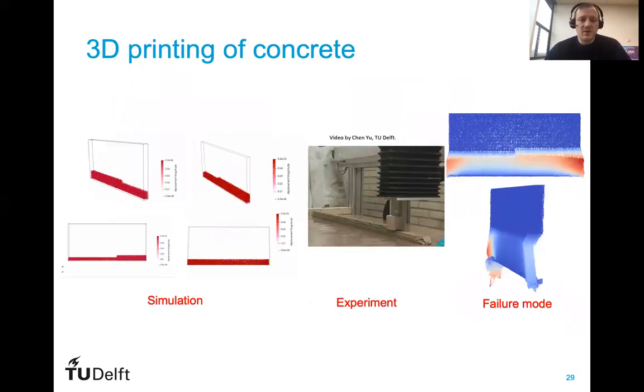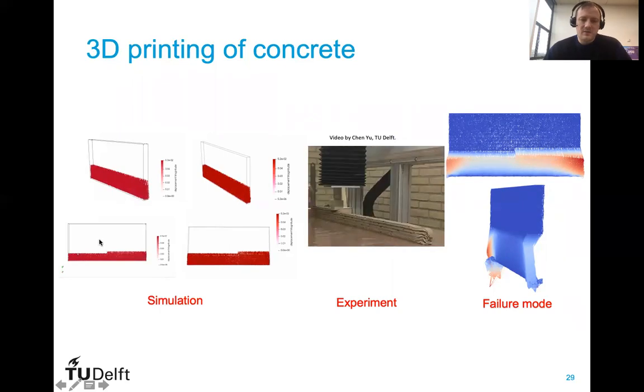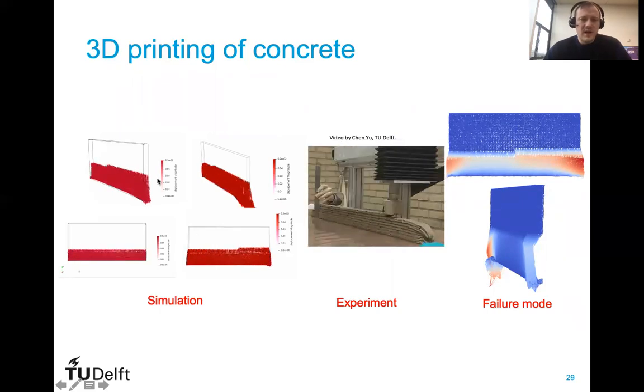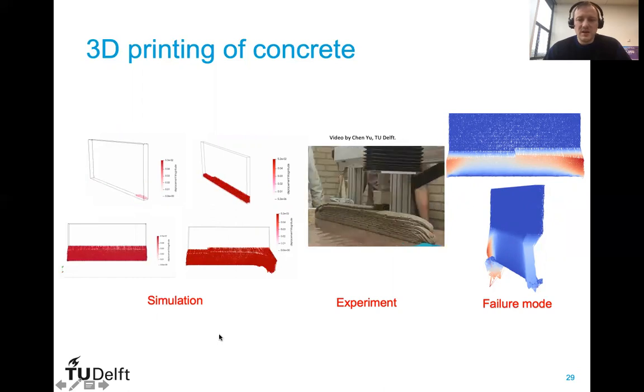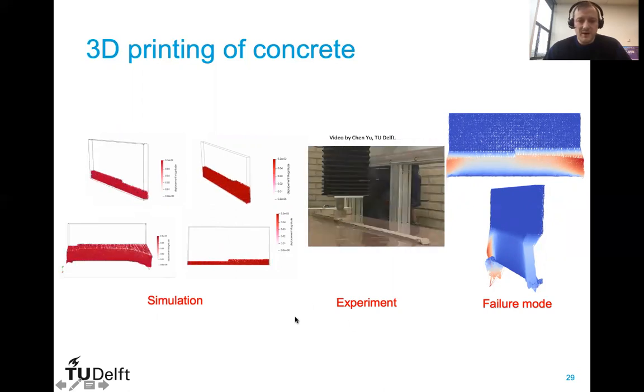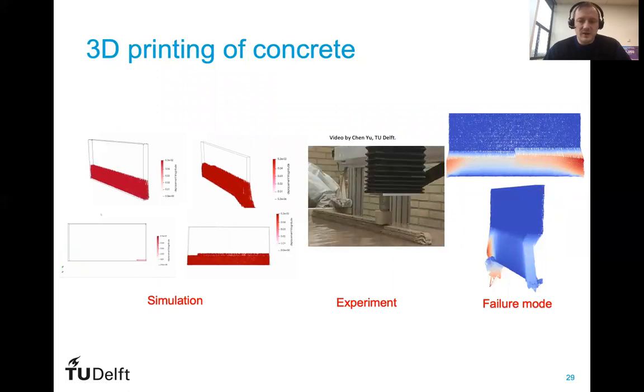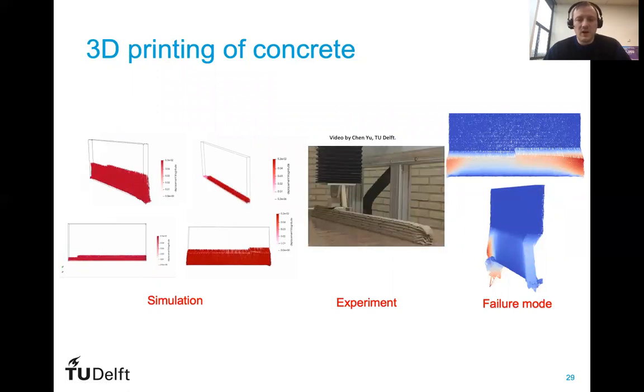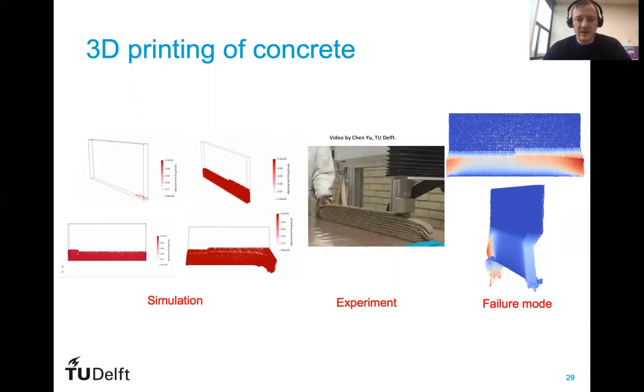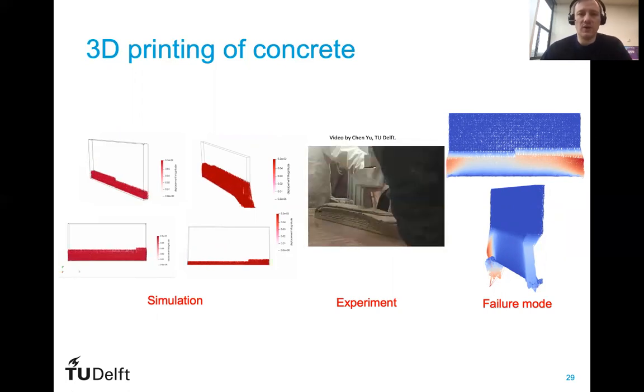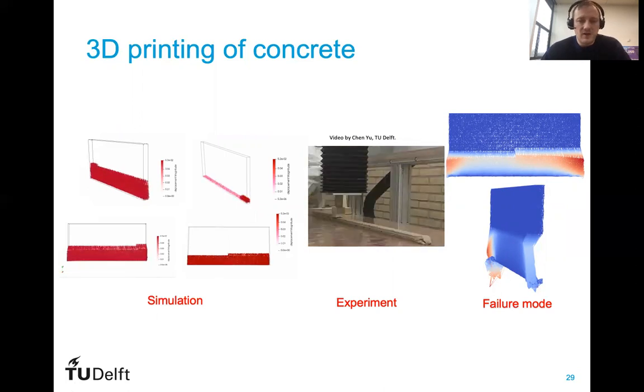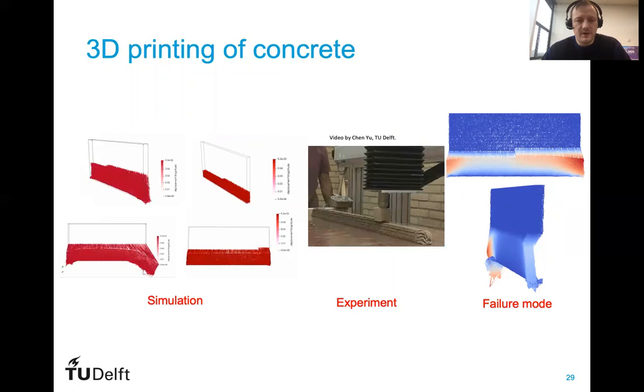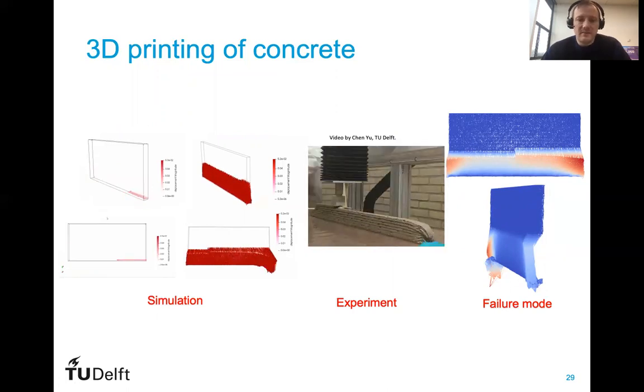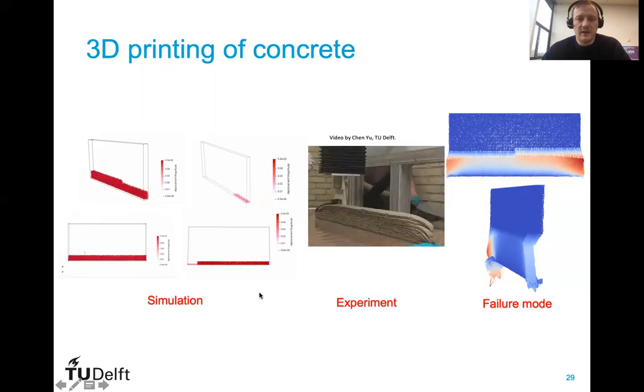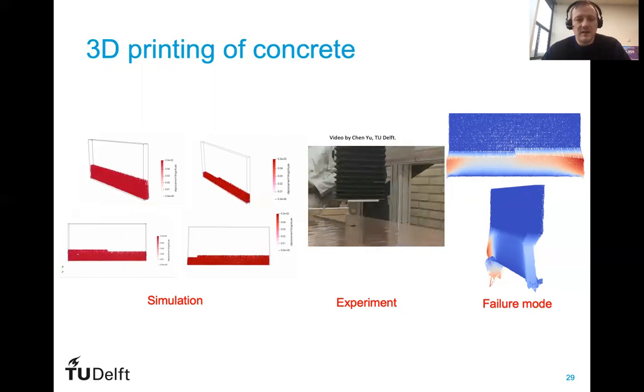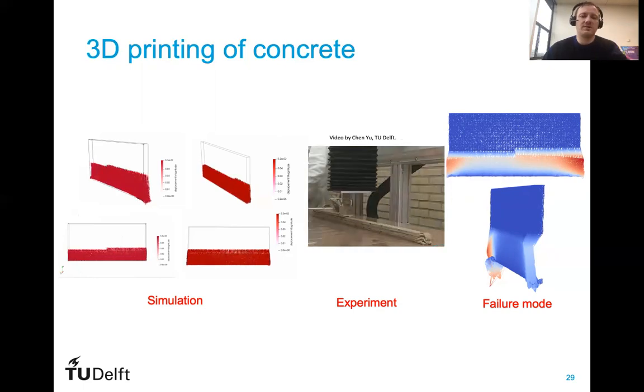The second failure mode is that of elastic buckling, and that commonly happens in, for example, wall structures. On the left-hand side, we see a simulation of the process, and on the right-hand side, we see an experiment. We can see that at this stage, we are able to simulate qualitatively the mechanism and the process, but we're still trying to fine-tune the model to get a better match in terms of quantity, in terms of how many layers can be sustained before the material fails in elastic buckling. So this is something that is very important if we are to optimize the printing processes in practice.